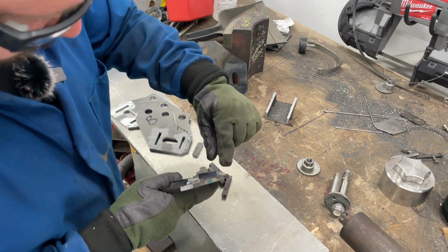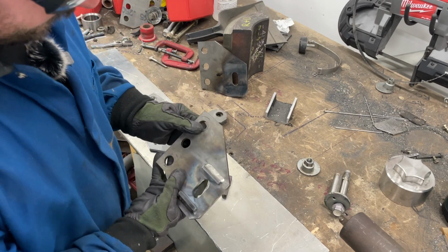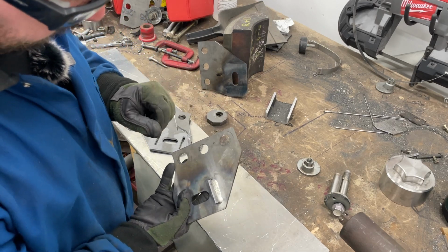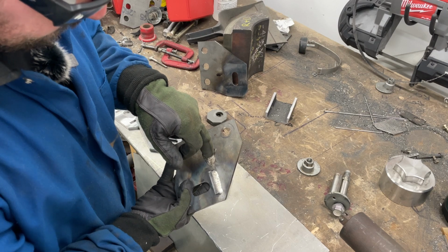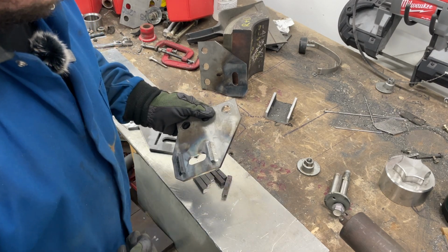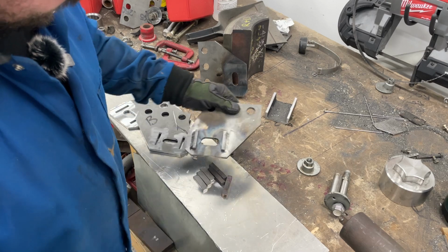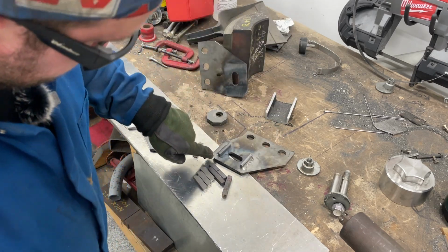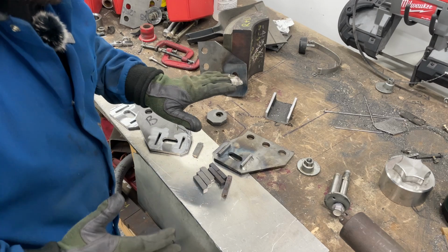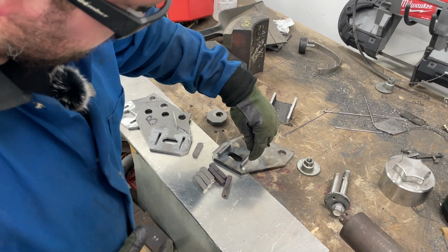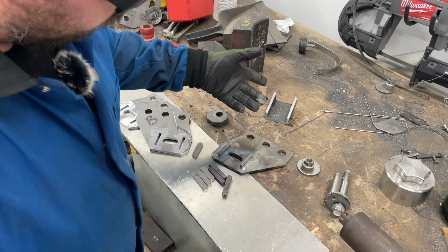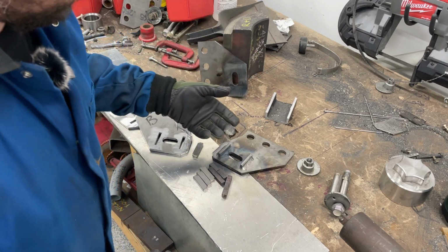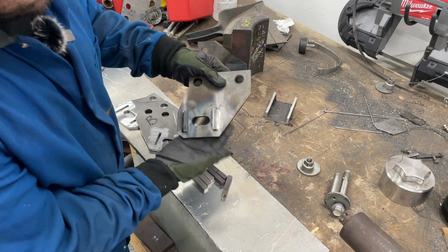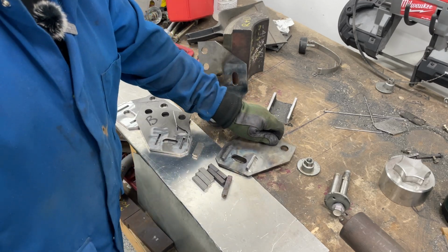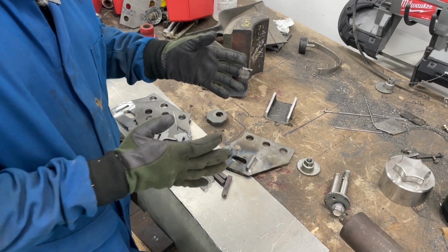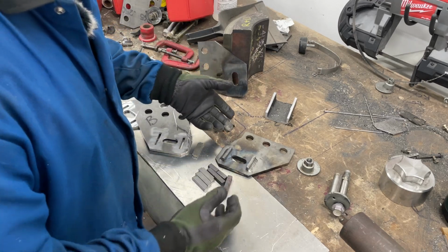For example, this little bit of cold lap right here on the edge of this weld, I'll fix that before I heat treat, but if that was underneath inside of this weldment, that could be a source for a crack. Fortunately, that's just my start and stop. I can grind it off, make it go away, and make it look nice and pretty like that side. But the stress relief stops the flaws in the weld from growing over time with fatigue, with the truck being pounded from racing use.